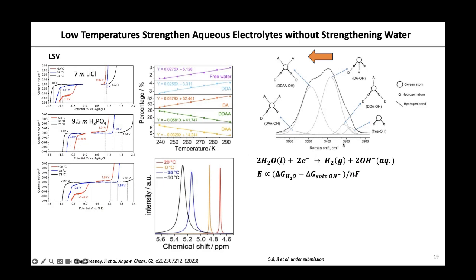Water is the reactant. The product is hydrogen gas and hydroxide. Hydrogen gas is leaving as a gas molecule, right? It's not going to affect the total energy of the product much. It's a constant. No matter how you transform the environment of the electrolyte, it's going to be the same for hydrogen gas. However, the hydroxide side will be different. If you have different chemical environment, you're going to have different solvation energies of hydroxide, right? This is the same thing for the oxygen evolution side as well. So if you tune the chemical environment for the product side, this hydrogen evolution reaction, the potential can be very much different. So that's the conclusion. We have some new result to show that this hypothesis is very, very promising.